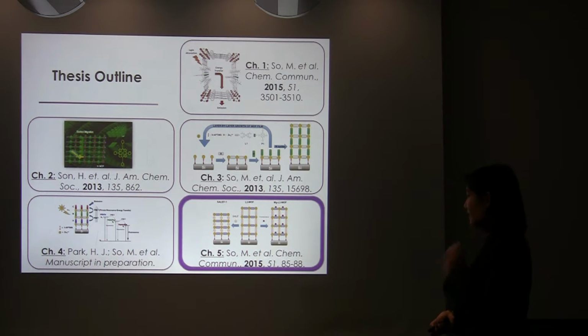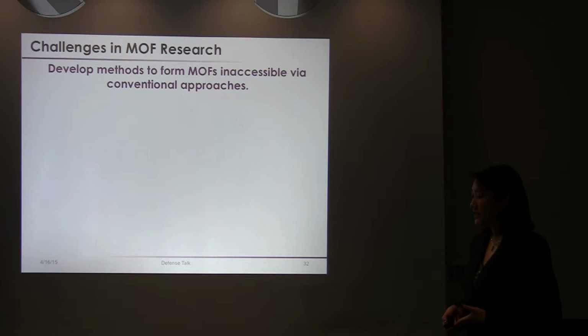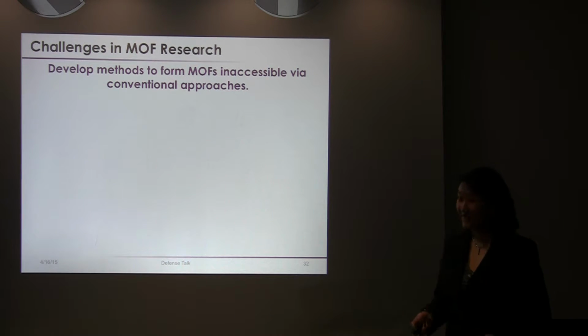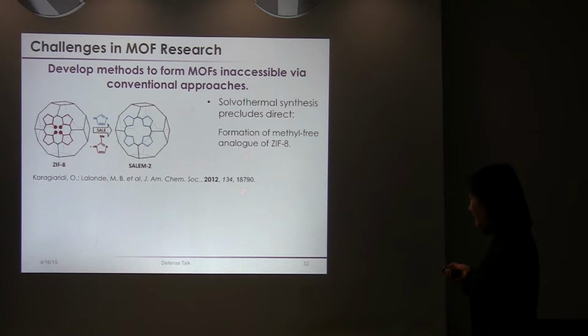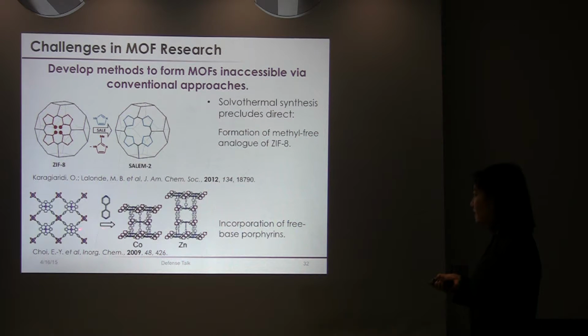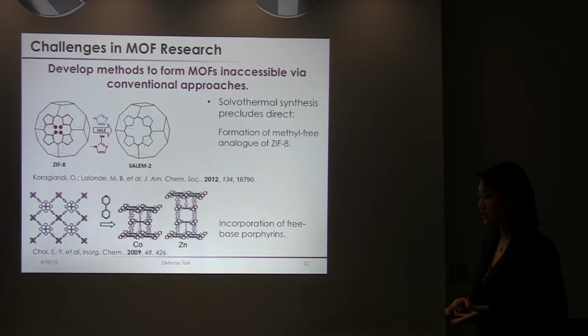So switching gears, now I will talk about what I did in chapter 5 of my work. So basically one of the current challenges in MOF research is that we need to develop methods that can form MOFs that are typically inaccessible by conventional solvothermal growth methods. For example, the formation of this methyl-free analog of ZIF-8 is typically not possible from conventional solvothermal synthesis techniques. Secondly, incorporation of free-base porphyrins into this MOF is also very difficult because, as I mentioned previously, these porphyrin linkers spontaneously metallate under these high temperature as well as acidic conditions. And so this precludes the formation of free-base porphyrins in MOFs.